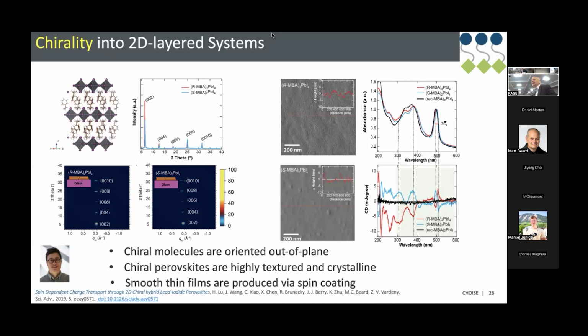And you can get these smooth thin films via spin coating. And so that's what's shown over here. You get nice, smooth, thin films that you can incorporate into electronic applications. And of course, you also get chiral transfer. So this is the inorganic electronic transitions over here, and you can see they all have optical activity.